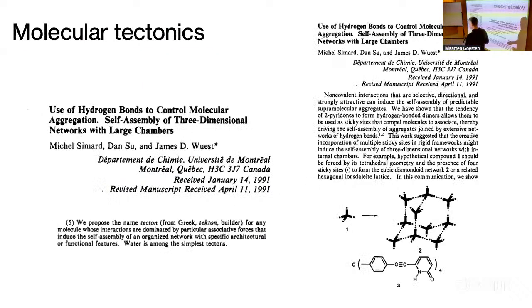And this is where molecular tectonics comes in. So this is a collection of papers from the early 90s by James D. Wuest, where he uses a geometrically well-defined building block. This is actually a tetrahedral building block. This is old-fashioned notation, so there's a 4 here. So this carbon here actually is a tetrahedral thing. And then it has these hydrogen bonding groups, what he calls sticky sites. So this molecule itself assembles into this porous organic structure, which is not very stable, but it gave rise